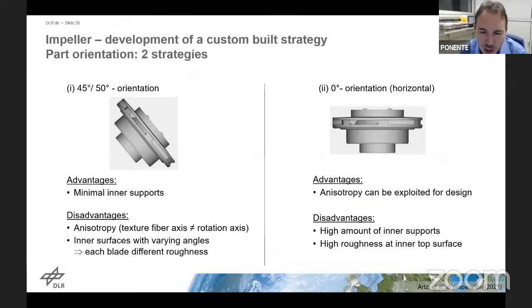The first aspect that we have to take care of when looking at manufacturing of a component, you probably all know, is the orientation of the component and the question of supports. For this impeller, we had the option of, let's say, 2 basic orientations, one a diagonal one, something like 45, 50 degrees with respect to the surface normal. This orientation has the advantage that you will need fewer internal supports to support basically the top surface, the downskin surfaces inside the part. But it does have the disadvantage that any anisotropy that the process, due to the directional vertical cooling basically gives you, will not be oriented along the high symmetry axis of the impeller itself. So you don't exploit the anisotropy here. It's diagonal in that sense.